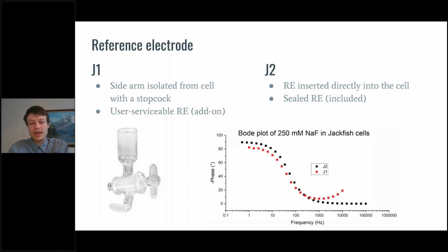And so here I'm showing a Bode plot, which shows the frequency response of each cell, which is filled with 250 millimolar of sodium fluoride. And you can see that for frequencies above about 1 kilohertz, there's this kind of curl upward in the phase angle of the impedance for the J1 cell. And so this really is indicating that you are measuring the impedance of the reference electrode and you're not actually measuring the electrical system that you intended to study. So for high AC frequency measurements, you might want to consider the J2 cell.